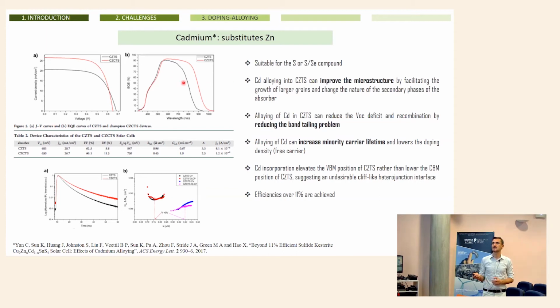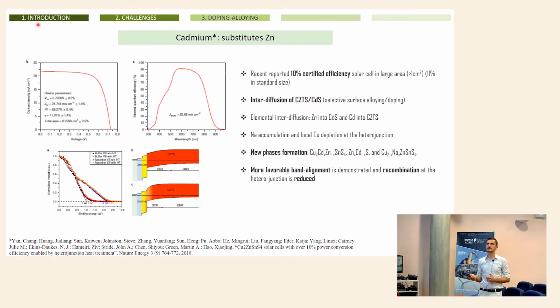Cadmium also substitutes zinc and can reduce the disorder in the material. This was already proved, and this gives very nice results. In particular, cadmium, for example, improved the microstructure of the kesterite and reduced the band tailing problem because it substitutes zinc, so this disorder is no longer possible. It increases the minority carrier lifetime, and then improves the efficiency. Then substituting zinc by cadmium in the kesterite is also a possible technological solution in the future. And using this, another world record was reported for this compound formed by copper, cadmium, zinc, tin sulfide, normally with around 20% of cadmium.